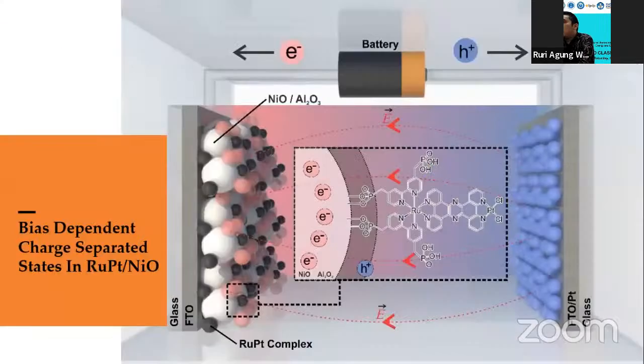Okay. So in the last section of this presentation, we now turn our attention to the effect of applied bias on the charge separated state stability in a quite similar system to ruthenium DPPZ sensitized nickel oxide. So here we have ruthenium platinum catalyst sensitized to nickel oxide, as illustrated in this